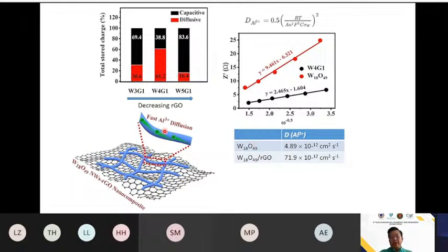So in this case, we can conclude that this fast aluminum ion diffusion is caused by the graphene oxide, and at the same time, aluminum ion can be trapped within the crystal structure of this tungsten oxide.